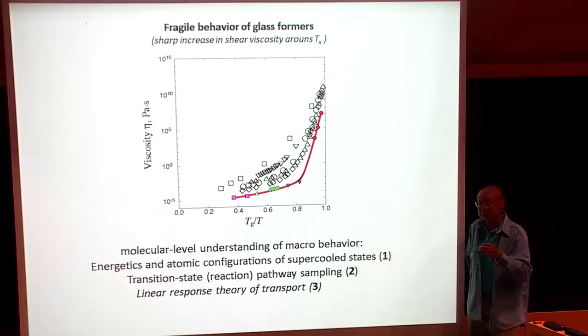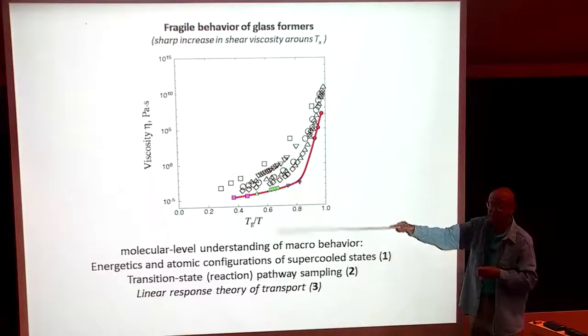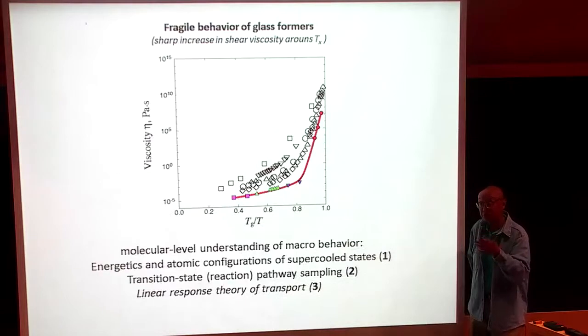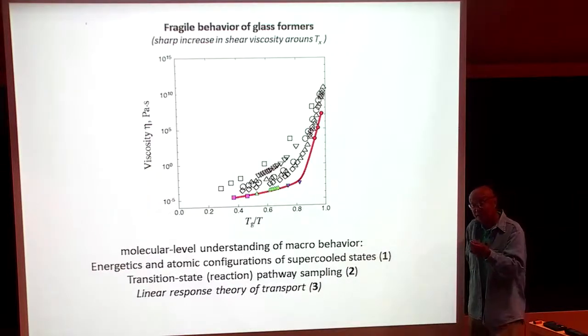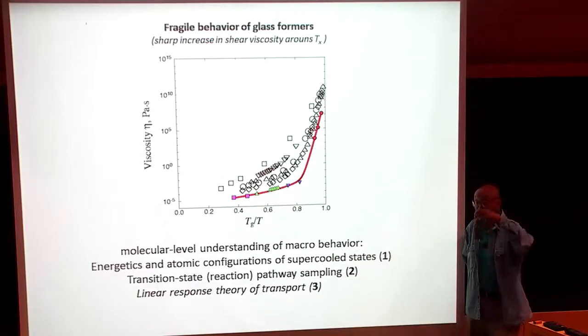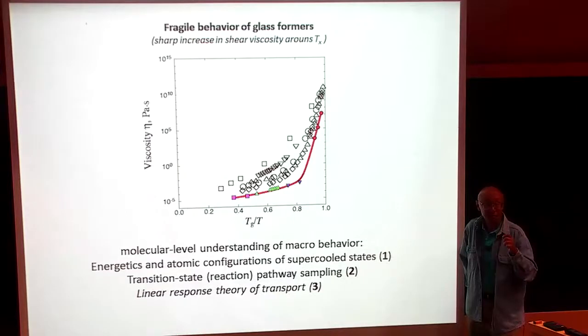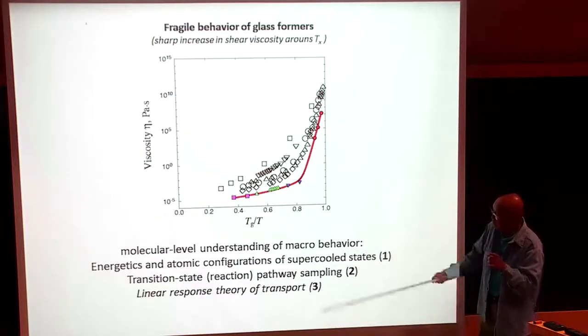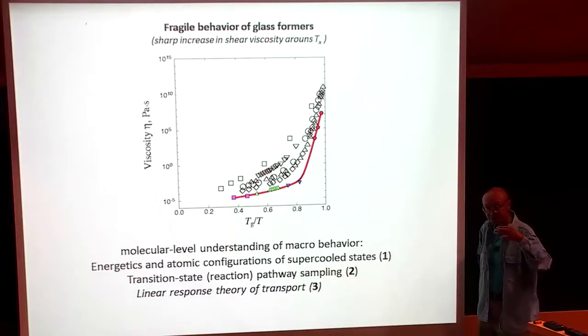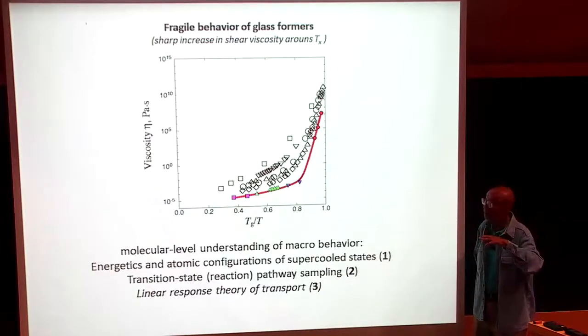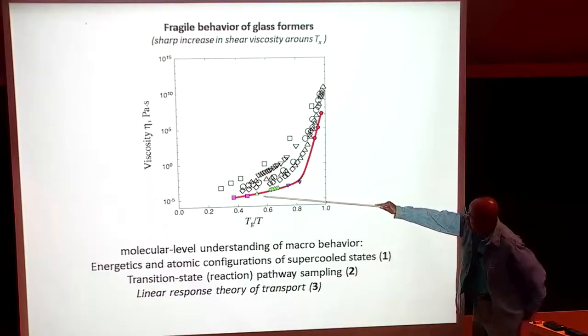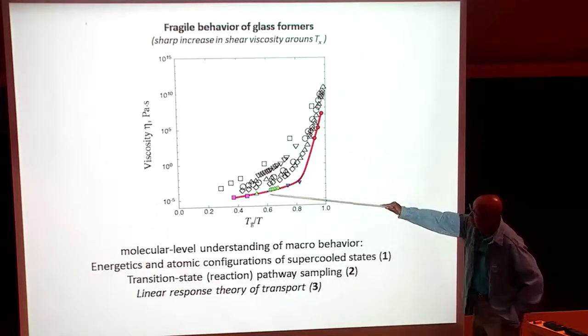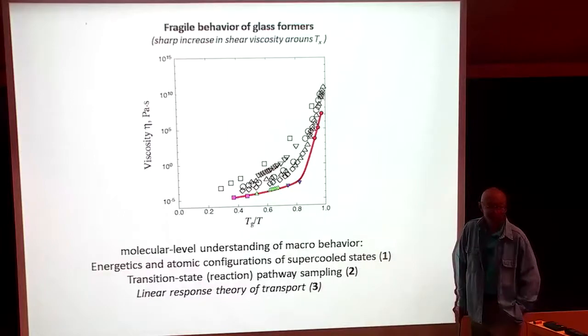So as you explore viscosity, I mean, after all, this is a transport phenomenon, so you talk about mobility, you talk about transfer. As you explore this energy landscape, it's not enough to just think about where the minima are, but you now need to go to saddles. You now need to get out of the deep ones and go to the next deep ones and keep on going. It's not just a single process. Once you're done with that, that's it. So this is the challenge to the transport. Now you have to generate various trajectories in your transition state pathway scenario on those rough energy landscapes that you have created. Therefore, if you want to calculate the viscosity at this fairly high temperature, or at this fairly low temperature, you can bet that you better use very different underlying energy landscapes, because that's what the system is doing.